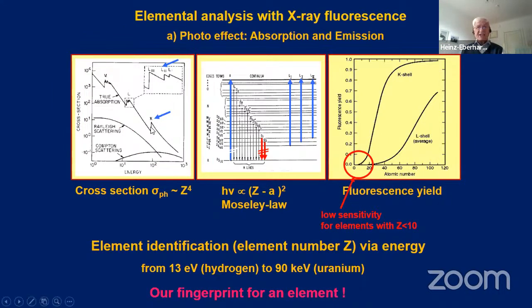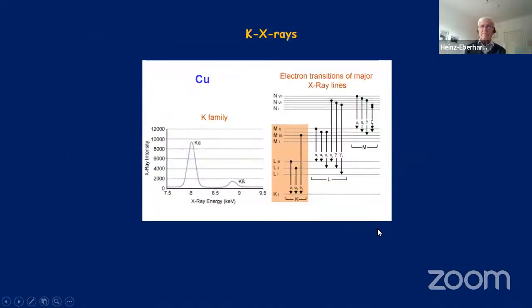That is summarized here. You get the edges in the absorption cross-section. The cross-section actually goes to the power of 4 for the elemental number. And here are the different lines coming out, the K lines. If you come down here, then one would have the L lines, etc. But the fluorescence yield is the competition between X-ray emission and electron emission. In the low Z regime, the elements lower than sodium or beryllium, and carbon and oxygen, very little radiation comes out, only electrons. On the high Z edge, we get the X-rays and not the electrons. And that one has to keep in mind.